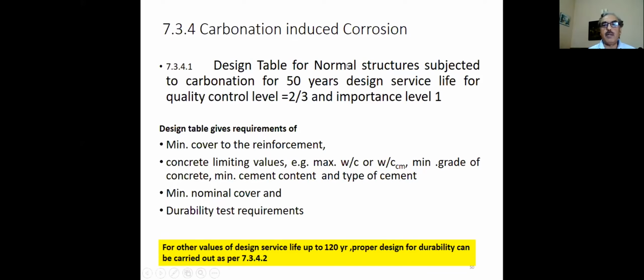We have provided a design table for normal structures subjected to carbonation for 50 years design service life, for quality control levels of 2 and 3 and importance level of 1. The design table gives requirement of minimum cover, limiting value of maximum water cement ratio, water cementitious ratios, cement content and type of cement, minimum cover requirement, and durability test requirements.